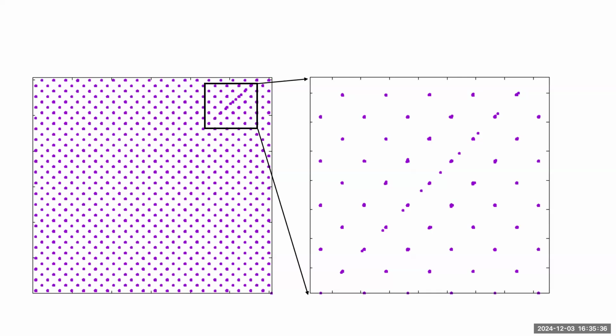The interstitial is not as simple as dropping a particle that just fits into an interstitial space in the lattice. It actually pushes out a column of nuclei along the body diagonal of the BCC lattice. Even though it's hard to see the depth here, all of these particles that misalign with the lattice are part of the interstitial defect. The interstitial is not one particle, it's a quasi-particle of 5 or 6 in a row that together become this larger scale defect.